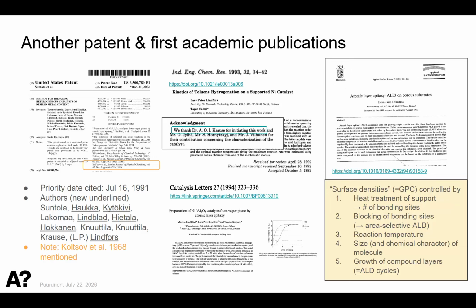So you can control the number of bonding sites, typically OH groups, by heating the support. So if you heat silica up to about 700, you have about 1 per square nanometer of OH groups. To decrease the loading, if you get too much in one cycle, you can block reactive sites. And this is something that's nowadays done a lot for area selective ALD. It has been used for catalysis already long ago. You can of course also play with the reaction temperature. It affects sometimes more, sometimes less. Of course you can then change the reactant. Some molecules are more reactive and more bulky than others, and to increase the loading, of course, doing more ALD cycles is an option. So these were already described by Eva-Liisa Lakomaa in 1994.